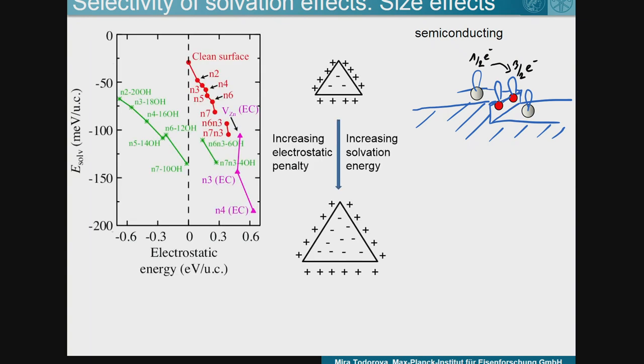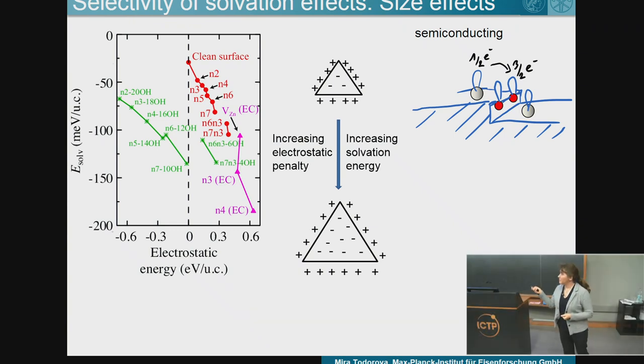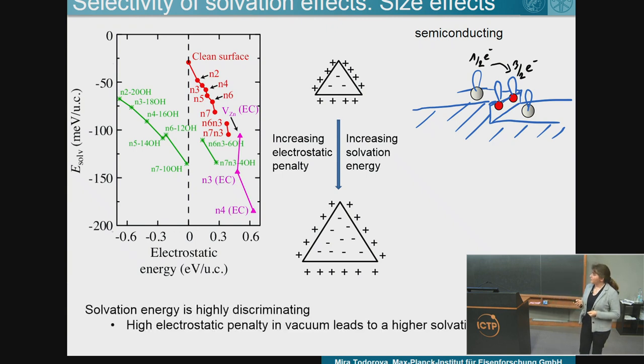Now, if we look at the electrostatic energy associated with this and the solvation energy that we gain, we can see that there is a correlation. What happens if I have a small triangle is that the oxygen and zinc dangling bonds are close by, so we don't have to pay a big electrostatic penalty to transfer an electron. If we increase the triangular size, then of course the bonds are further away, and therefore these structures become less favorable in vacuum from an electrostatic point of view. And what the solvent does is to screen this unfavorable electrostatic interaction, thereby stabilizing structures which have a high electrostatic penalty in vacuum.